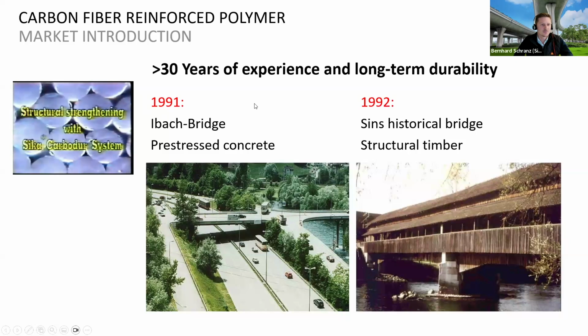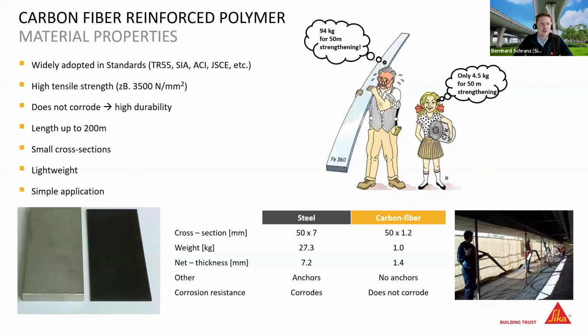And yes, why do we trust in carbon fiber? At the moment, it's already widely adopted in all sorts of international standards. This is from the standardization side, which is a sign, of course, for wide adoption. So we then have very high tensile strengths. The material does not corrode, so it's highly durable. You can roll it up to lengths of up to about 200 meters. You have, in the end, very small cross sections for strengthening. It's very lightweight, and it's also very simple. So if you compare, for instance, the equivalent steel to carbon fiber, it's several times smaller, let's say, if you make a strengthening with a carbon fiber solution.